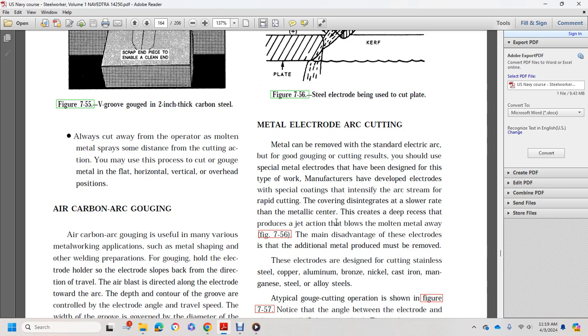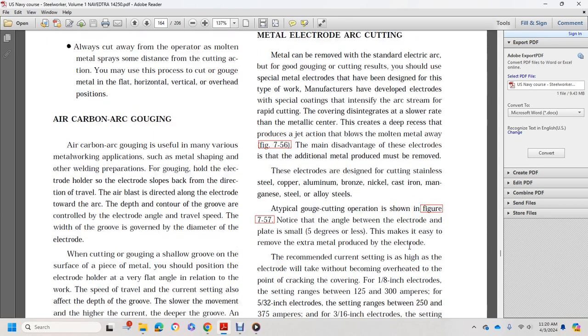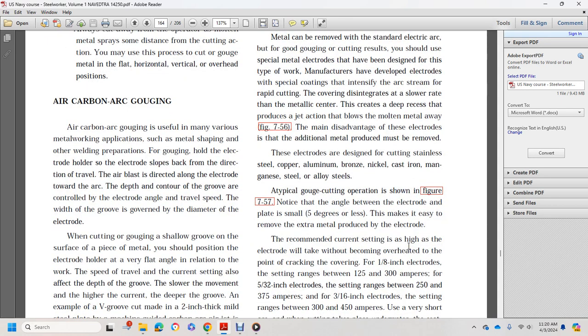Developed electrodes with special coatings produce an intense arc stream. The rapid cutting coating disintegrates at a slower rate than the metal core, which creates a deep recess. The jet action produced blows the molten metal away. Figure 756 shows the main disadvantage of these electrodes. Additional metal produced must be removed. Electrodes are designed for cutting stainless steel, copper, aluminum, bronze, nickel, cast iron, magnesium, steel, and alloy steels.